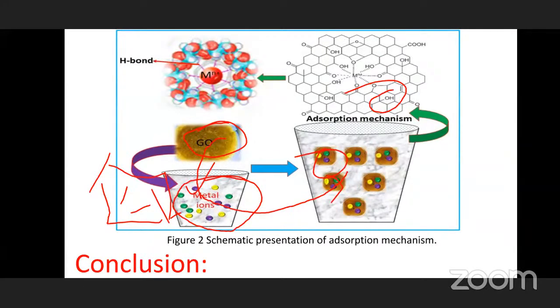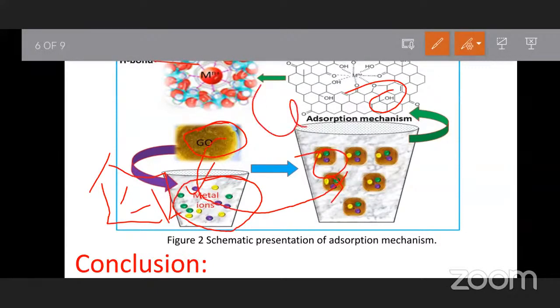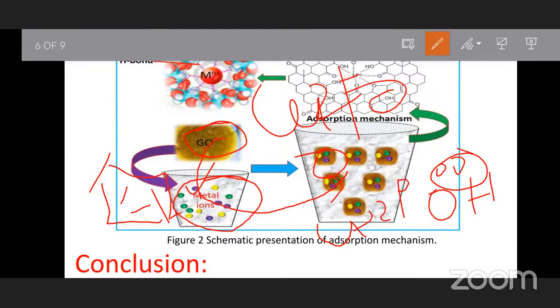So through the OH group, keto group or aldehyde group, metal ions like copper 2 plus or 3 plus, lead 2 plus can be adsorbed by the graphene oxide. The OH group, or any oxygen containing group, contains a lone pair. This lone pair can act as the negative side and the metal ion is the positive side. So it can form a coordinate bond, or it is an attraction through ionic or dipolar attraction. Okay, so it can form a hydrogen bond like this.